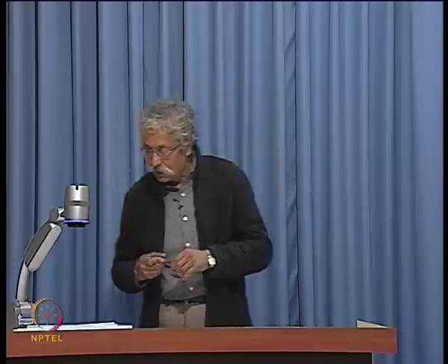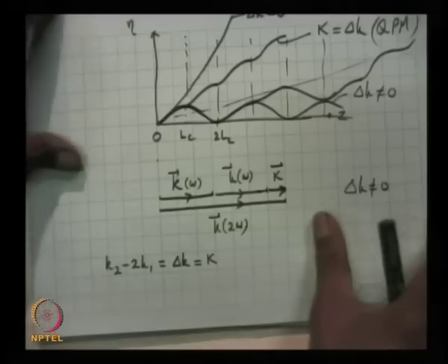Okay, so there is a first order quasi phase matching, third order quasi phase matching, fifth order quasi phase matching, because the period required here is much larger, 3 times, so 10 microns. But what is the price I will pay? The Fourier coefficient will be small, so the effective nonlinearity will be small. So all this I will get from this analysis.